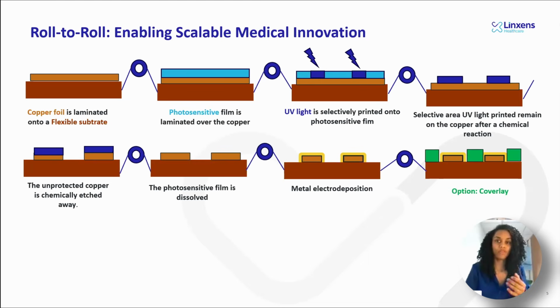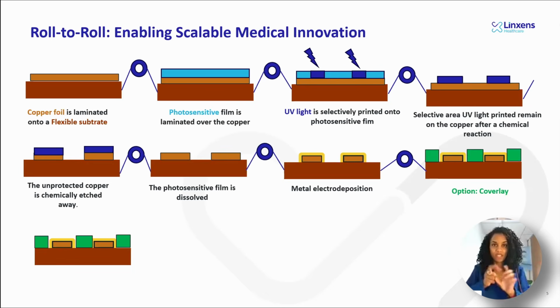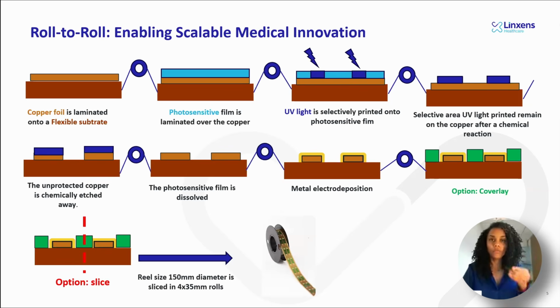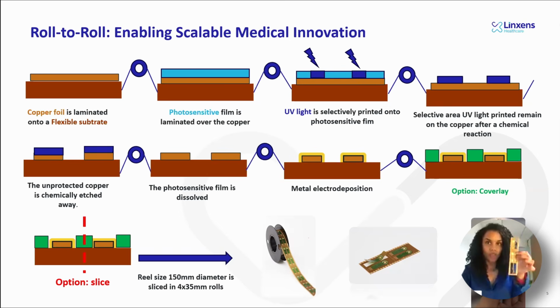So if, for example, you want to have a coverlay with a specific property, we have the possibility to laminate this coverlay around the electrodes. We can also change the packaging size of the electrodes. So initially, you start with a system where the diameter of the electrode is 15 centimeters, but we have the possibility to slice the electrodes and obtain something shorter. And in general, the width is around 35 millimeters.